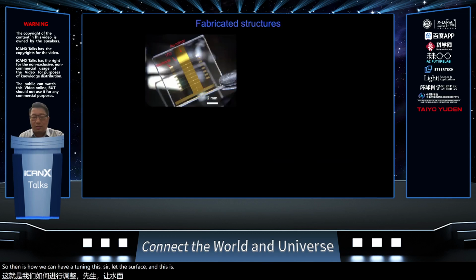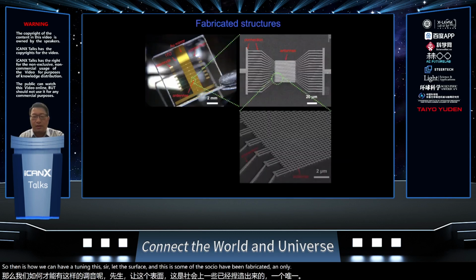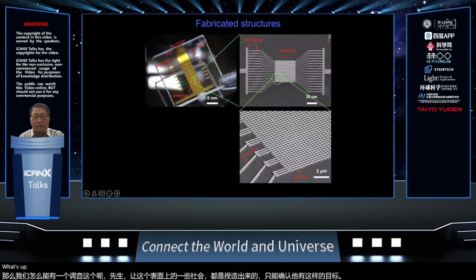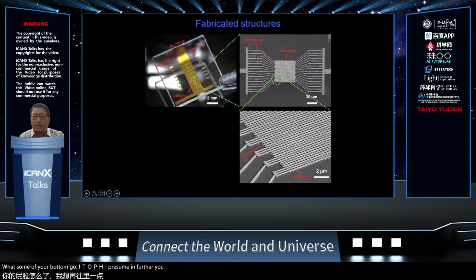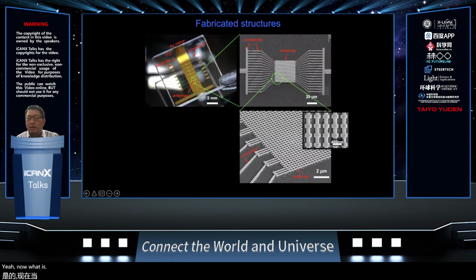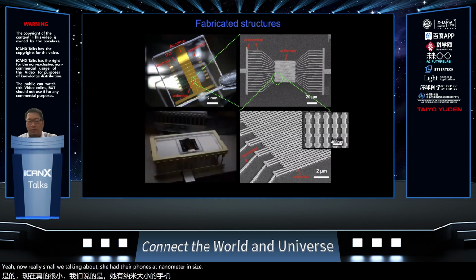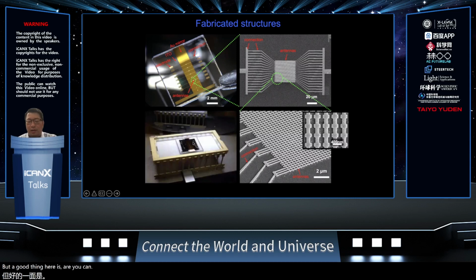And this is some of the structure we fabricated already a couple of years ago. For example, we have a bottom gold ITO here. If you zoom in further, you see we have all the connections. We have the antenna inside. If you zoom in further, you see the antennas here. They are really small, about 300, 400 nanometers in size. The good thing is you can apply the voltage while looking at the optical property, so that you can actively control it.